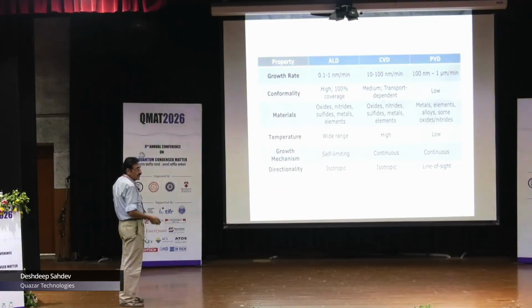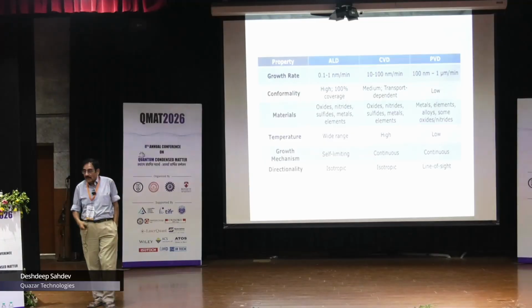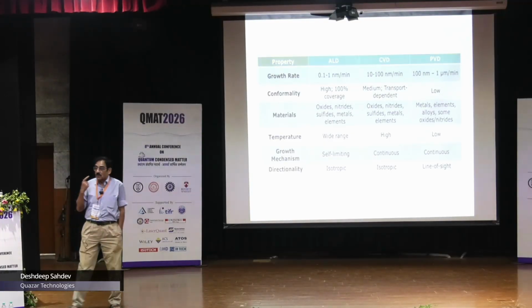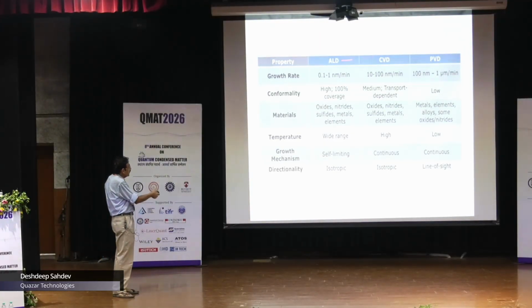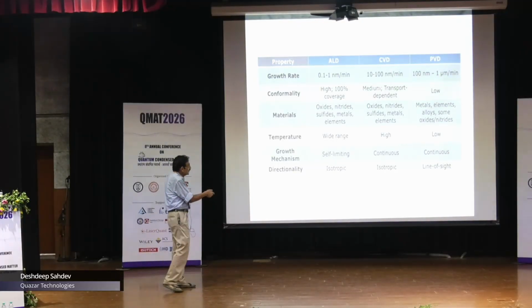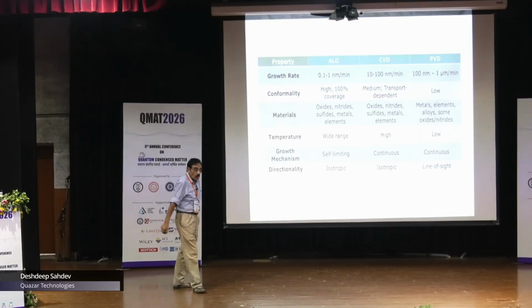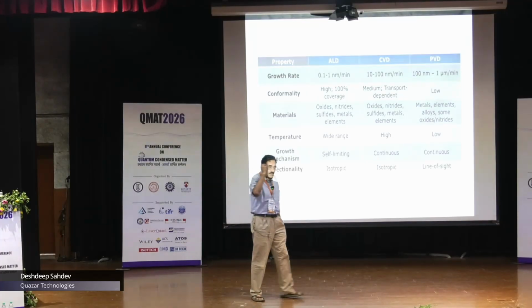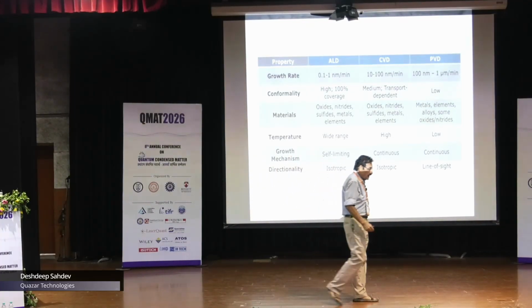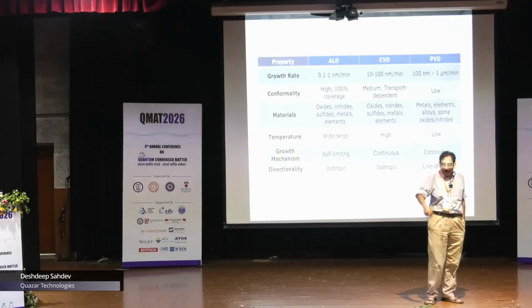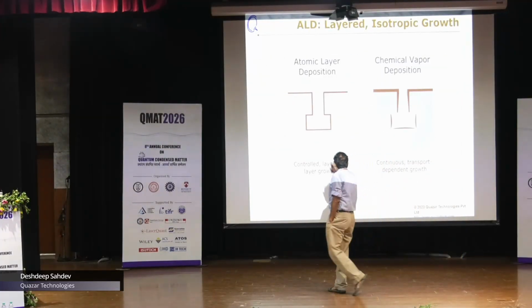After that, the next thing that we did was to move on to making an atomic layer deposition system where the control is one atomic layer at a time. If you grow with physical vapor deposition, you can grow at the rate of about 100 nanometers to 1 micrometer a minute. With CVD, the control is a little more: 10 to 100 nanometers per minute. And with ALD, it is 0.1. It's a pulse system. You send in pulses of precursors, and with every pulse, you get one layer.